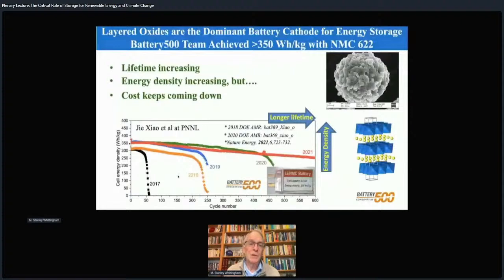And we're doing this through what is called a Battery 500 Consortium run by the Department of Energy in the United States out of Pacific Northwest National Lab. And this is a typical layered oxide. It's what we call meatball morphology. The primary particles are 100 to 200 nanometers, the secondary particles are about 10 microns across. They pack very well, so they make a dense cathode. What we've been able to do over the last 5 years is increase their lifetime, increase their energy density, and at the same time, the commercial cells are coming down in cost. But as I say, there are issues with the safety here.